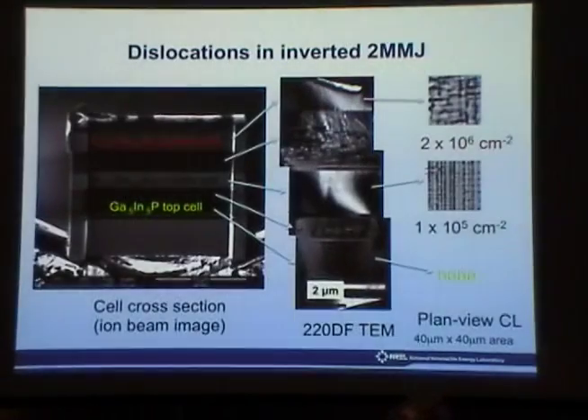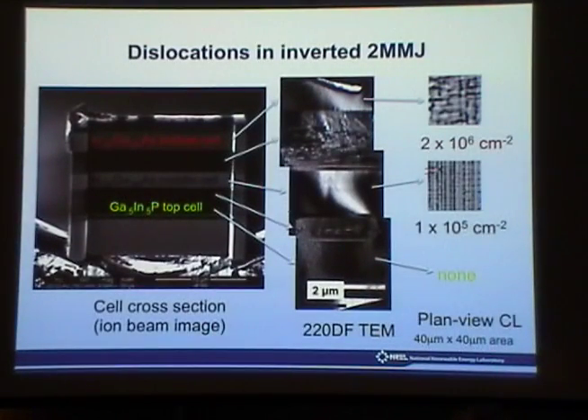So if you look at a TEM version of that one, what we did is we took a FIB, a focused ion beam, cut out a small section, did a cross-sectional image, and then TEM. So here's the substrate, here's the top, middle, bottom cells, and then, again, it doesn't come out so well in projection, but there's a graded layer here and a graded layer here. And if you look at the TEM dark field images, those two graded layers are chock full of dislocations. But the materials of the solar cells here, here, and here are actually very, very clean.